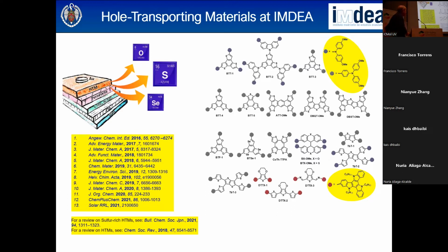Okay, but there is something interesting because in these molecules, because they are planar, you can consider pi-pi interactions between them, but also sulfur-sulfur interaction, which is very efficient, by the way. But in addition, sulfur could interact with those components of perovskites, for instance, iodine or lead. And well, this is important. The second consideration is that all these molecules can be synthesized in gram amounts at very low cost. Actually, we carried out the study of this, and many of them could be prepared at around or lower than $50 per gram, without considering fabrication in big amounts. And the new molecules have good thermal stability, as I will show you later on.